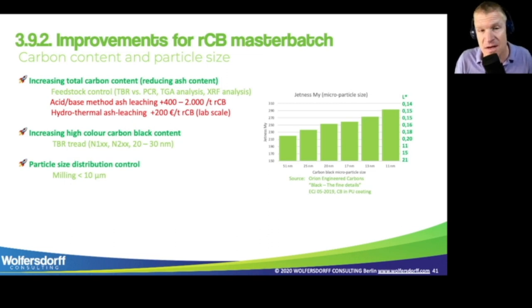And also, if you think about the large volumes of recovered carbon black in a typical plant, thousands of tons, if you have to run all these through an acid and a caustic, this perhaps has also some safety issues. There's a new method, a hydrothermal ash leaching. Hydrothermal meaning just with water and temperature. It promises to be cheaper, about 200 euros per ton, but that particular company is only at lab scale, and I find they first have to prove the commercial viability for, you know, thousands of